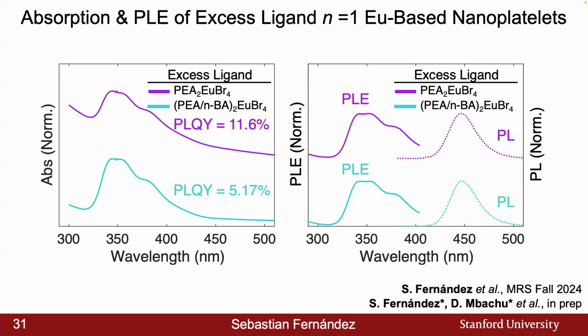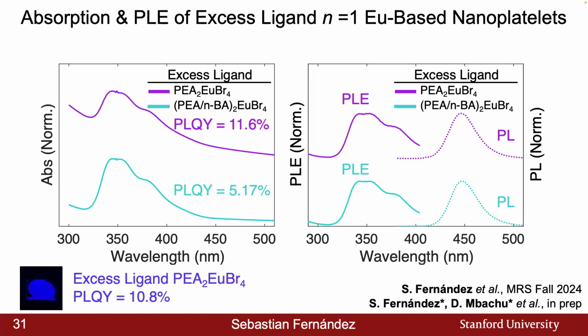And just as a brief note, when we drop cast them and centrifuge out these nanoplatelets, these excess ligands, the picture doesn't do justice, but it's really bright, dark blue, has a PLQY of around 10.8%, really showcasing the ease of how we can create these materials and hopefully integrate them into devices and finish the current material characterization that we're looking at.